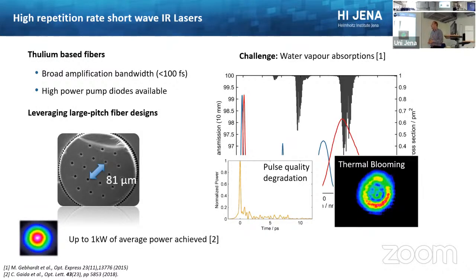Despite that, we have been quite successful over the last years in following the progress of ytterbium, now with thulium, and have systems that work at high average powers up to 1 kilowatt with ultra-short pulses, but also systems based on large pitch fibers that can emit ultra-short pulses with a few hundred microjoules of pulse energy. And today, I would say the performance is very comparable to ytterbium already.